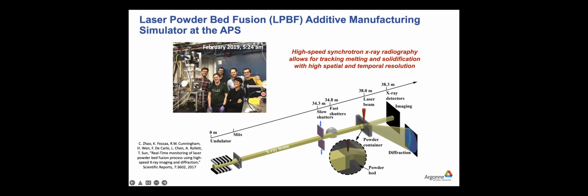Basically what this enables is us to do high-speed synchrotron X-ray imaging and diffraction of the melt pool dynamics and of the solidification process at really high spatial and temporal resolutions. This is shown schematically down here where the X-ray beam comes in. And over here, we have the location of our sample, and our sample can take a few different possible geometries. We can have a metal cross-section. We can have a metal cross-section with a powder layer on top, or we can have a packed powder layer in between glassy carbon plates.